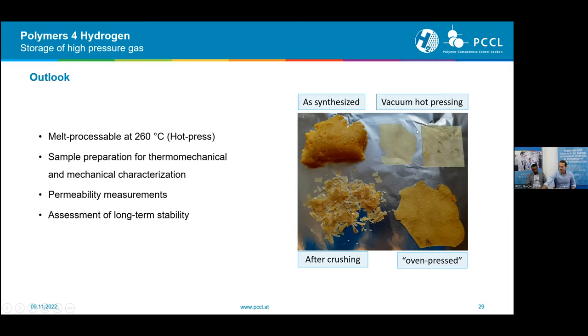And on the right, you can see a picture of that. So after the synthesis, it looks like this big sponge, which comes from drying it in the oven. So the water, when it evaporates, just expands. We pressed a bit already in the oven and crushed it into smaller pieces. And after that, we placed it in this vacuum hot press. On the left hand, you can see it for 260 degrees Celsius. And on the right hand, it was for 250 degrees Celsius. And here you can see some unmelted pieces. It would also work for 250 degrees Celsius, but it would need a longer duration.